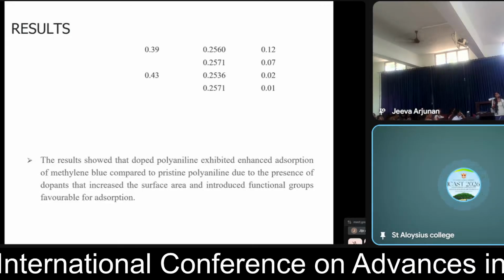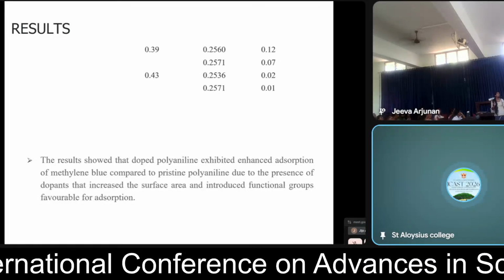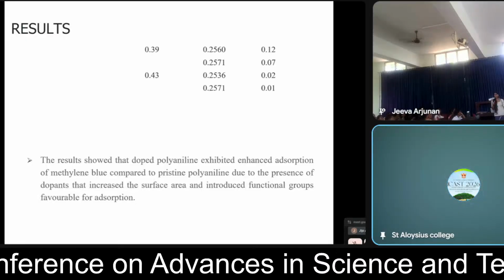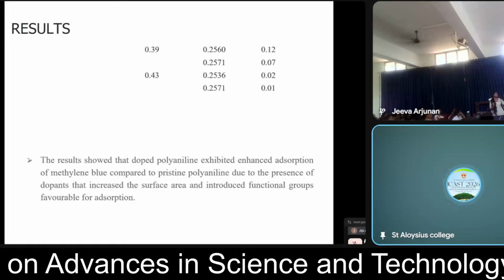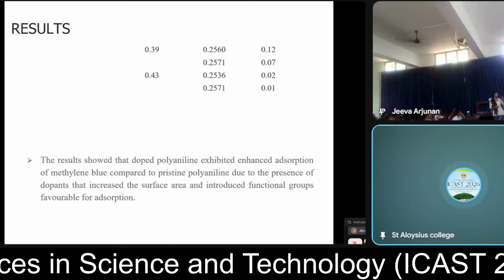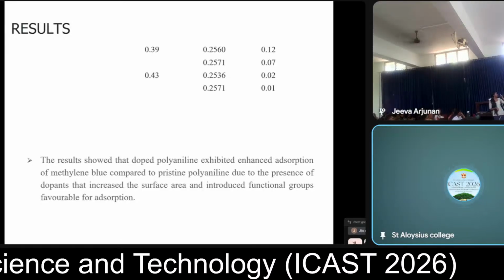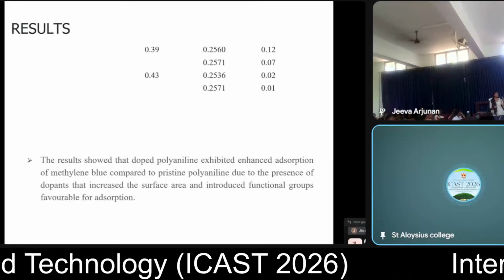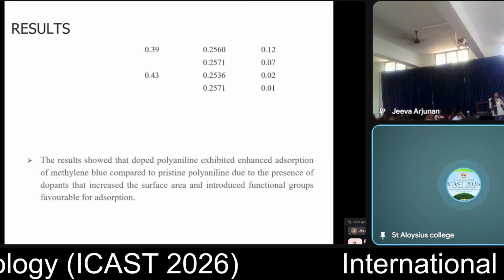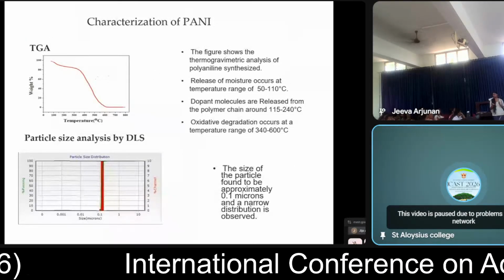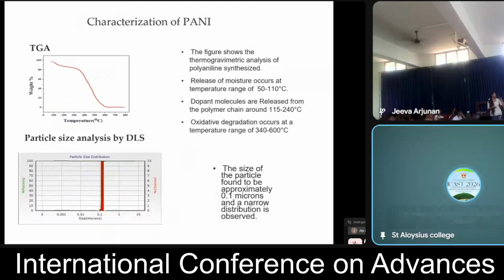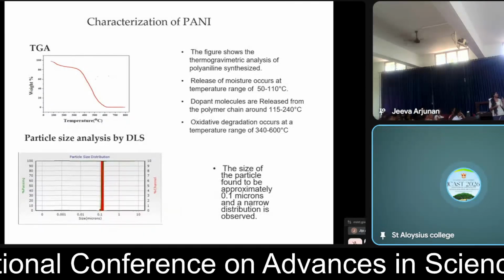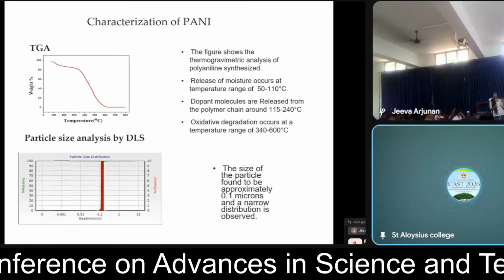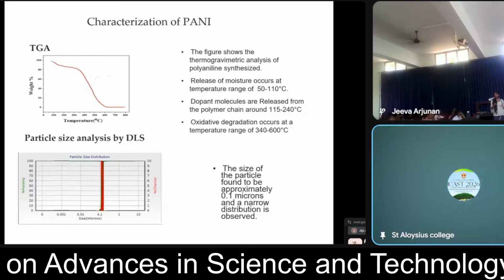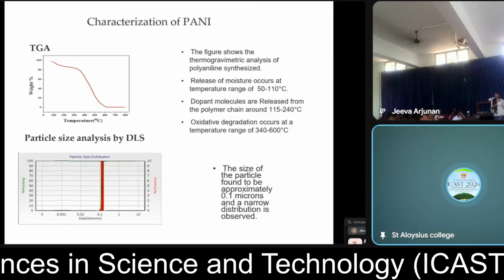The particles are agglomerated with a size of approximately 100 nanometer, and it shows a block and spherical structure. And we also take TGA and particle size analysis. On TGA, at 50 to 110 degrees Celsius, the release of moisture is occurring, then the dopant removal occurs at 115 to 240 degrees Celsius, and the oxidative degradation occurs in the temperature range of 340 to 600 degrees Celsius. By analyzing the particles, we find the size is approximately 0.1 micron, which is equal to 100 nanometer, which we already got from the SEM analysis.